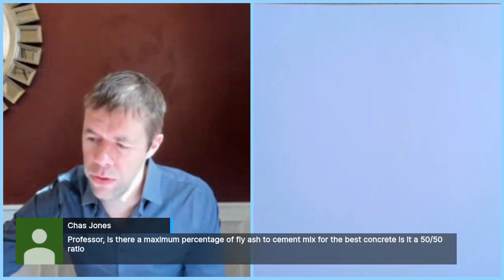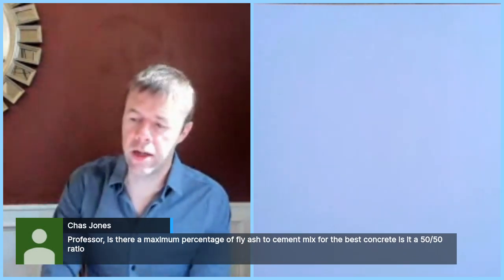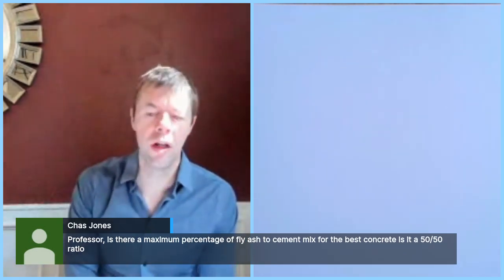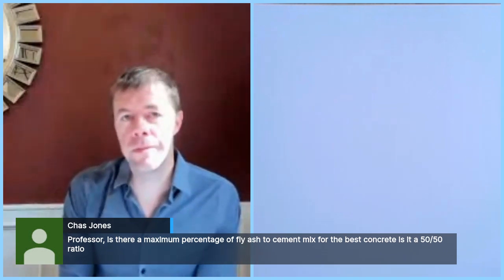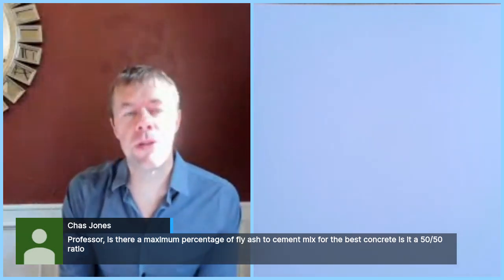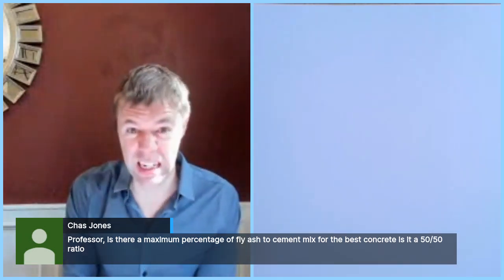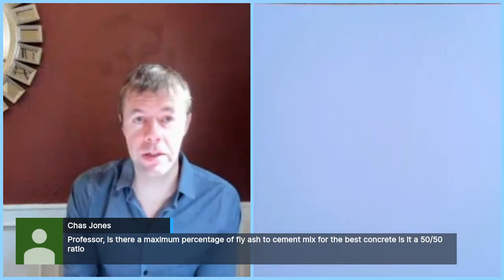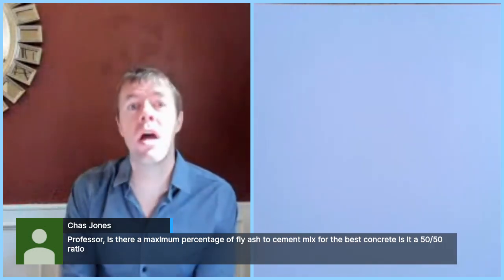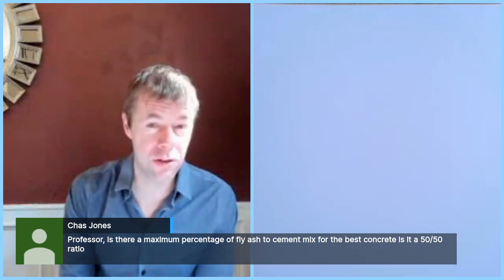Chas wants to know, is there a maximum amount of fly ash to cement mix for the best concrete? So Chas, no, there's not some maximum amount. I've seen mixes with 80% fly ash. Yeah, 80% fly ash, 20% cement do amazing things. You have to get the right fly ash though.